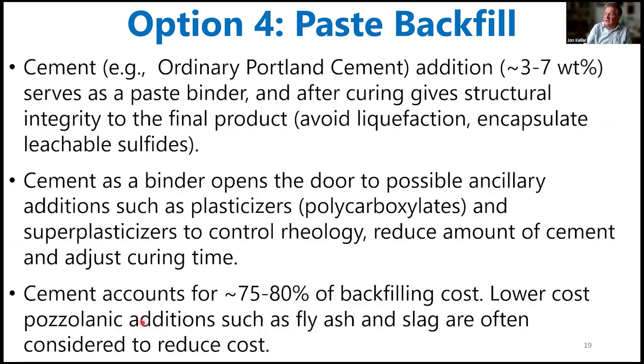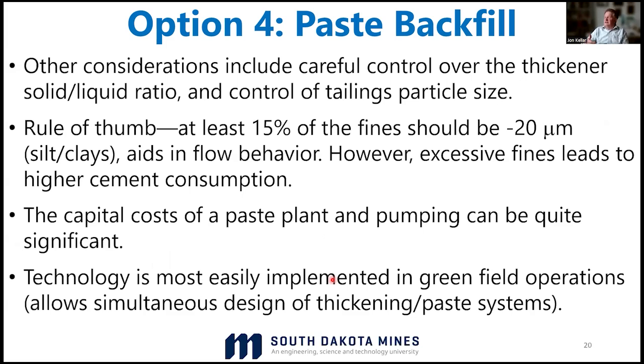And so you can lower that cost perhaps by adding one of these pozzolans that will enhance the cement chemistry. Fly ash and slags are often considered to reduce the amount of cement and the cost of creating the paste backfill. Other considerations include control of the solid liquid ratio coming out of that thickener, and control of particle size. Here's a rule of thumb I found: at least 15% of the fines must be minus 20 microns, down into the silt clay region. So if your tailings don't meet that, you may have to blend the system to include finer particles. But if there's excessive fines, your cement consumption is going to go up.